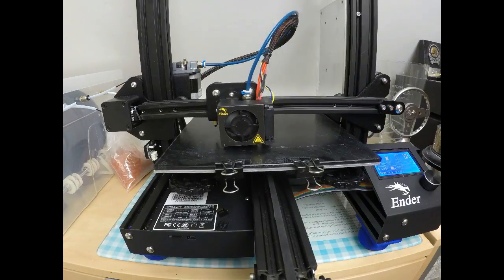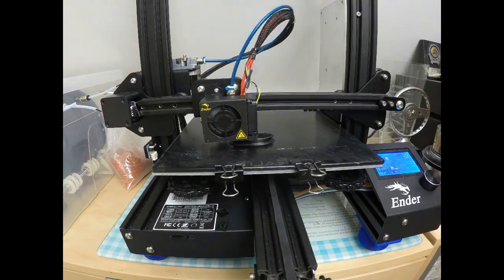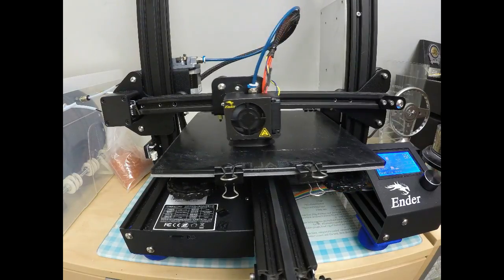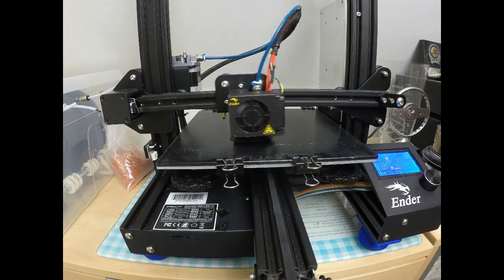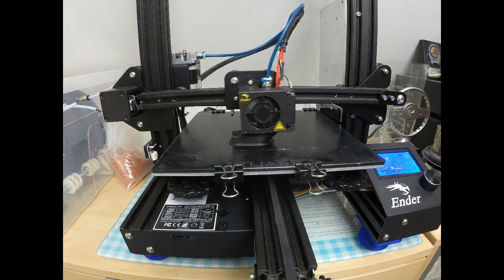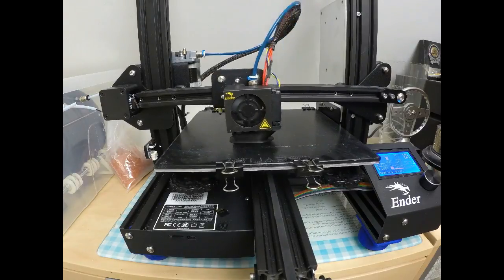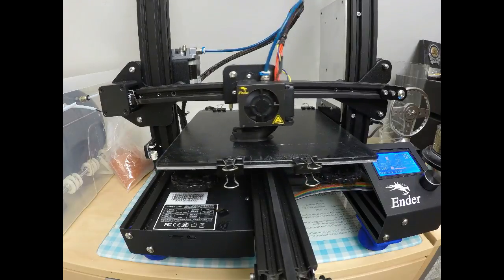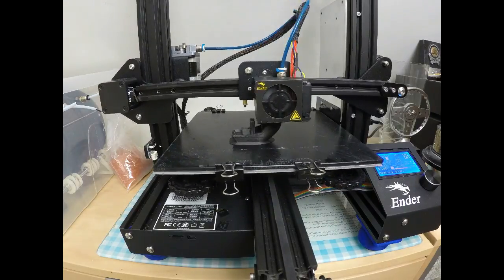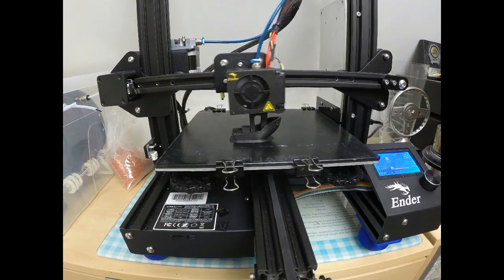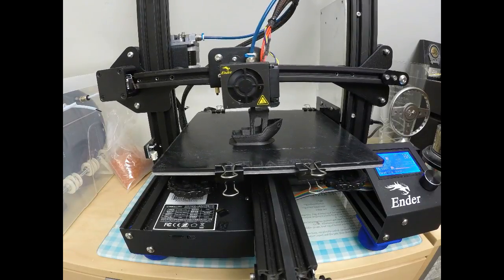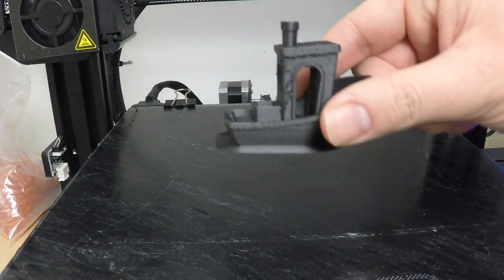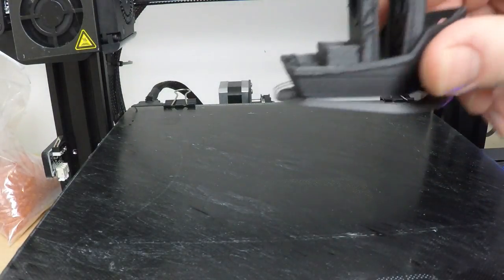So you may have noticed I flipped the ultra base and used glue stick on the clean side. I was having lots of first layer issues. Couldn't even run my level test. The nylon would just ignore the bare base, the textured side of the ultra base and just follow the nozzle lift off. So it just wants to stick to itself. As soon as you've got a first layer down, you haven't got a problem. It'll print all day long. It's getting that first layer down right. That's the critical thing. So my advice, don't even bother with anything else. Just flip the glass, smooth glass, layer of glue stick, and you're away. Apparently Garolite works quite well, but I don't have any. I don't want to buy any, but this setup works beautifully.